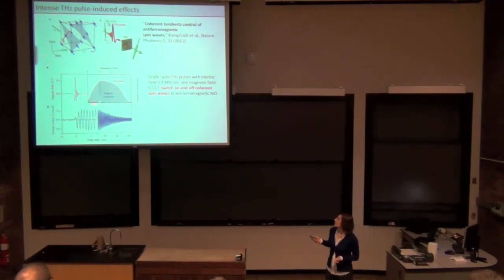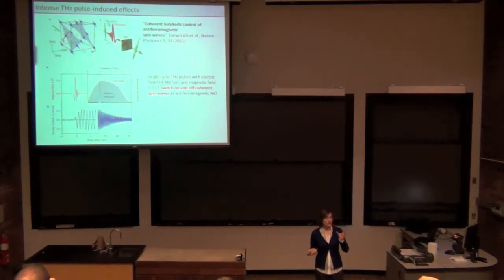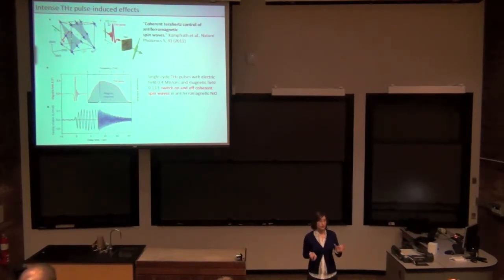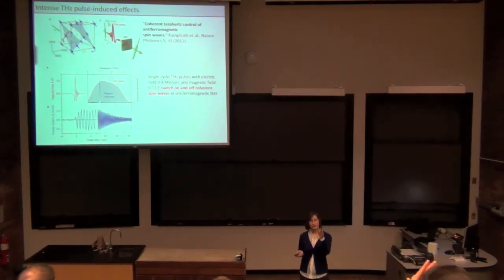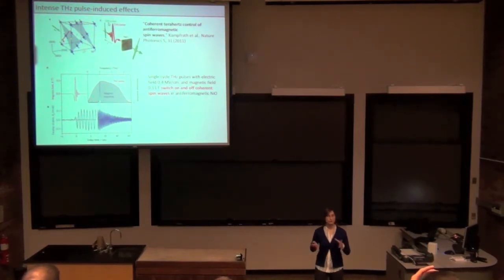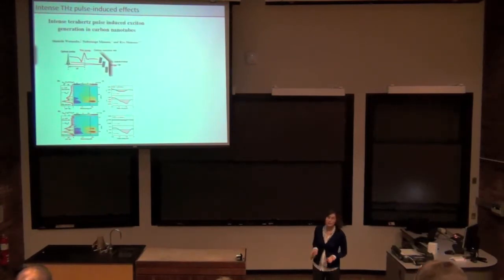They sent a terahertz pulse in, and then probed the sample with a very short, 8 femtosecond pulse, and looked at the Faraday rotation. What they get is a coherent oscillation, which persists for quite some time. When they take the Fourier transform of this, they get exactly this magnon mode. So they successfully launched the spin wave mode into this material. I don't have this picture here, but after this has been launched, they can come in with a second pulse, and depending on the phase relationship, they can either kill it or enhance it. So now you have a way, in ultrafast fashion and without any contacts, to turn on and turn off spin waves.